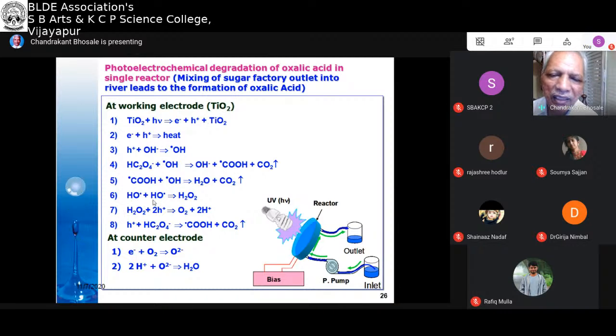OH radical and OH radical give H2O2, and that H2O2 reacts with 2H plus and gives O2 plus 2H plus, and this H plus again reacts with the oxalic acid, and we get COOH radical plus CO2. So at this working electrode of TiO2, you will find that CO2 escapes at the surface of the TiO2.